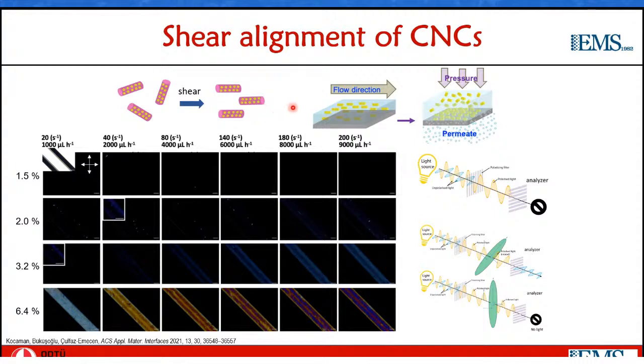So basically they align in the direction of flow after a certain shear rate and after a certain concentration. So what we did here is we took stable sols of cellulose nanocrystals. We filtered them on a porous support in cross-flow filtration, where they could align in the direction of flow, and we could tune the extent of alignment by tuning the flow rate. And then during this cross-flow filtration, we basically form a filter cake of cellulose nanocrystals on a porous support, and then by physical or chemical means stabilize the cellulose nanocrystal cake on the support and end up with a composite cellulose nanocrystal membrane.